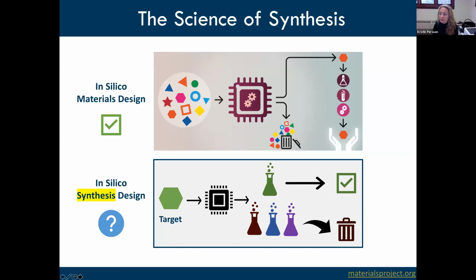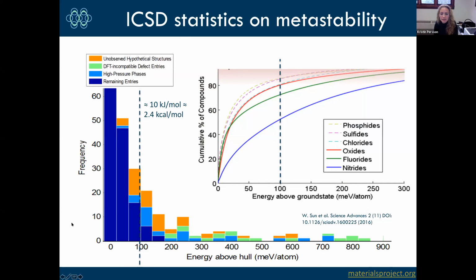So my group is doing a fair amount of this, and I'll give one example of the insights that we have garnered from looking at how we can bound synthesis space. If you look at some statistics out of the ICSD, the ICSD contains the materials that have been made. The Materials Project contains a lot of the ICSD structures and chemistries, but also our own hypothetical materials, things that we don't know if they can be made. And if you take just the statistics on the things that have been made, you can see that synthesizable materials really do correlate with energy above hull. That is something we can compute. We can calculate the energy of all the different competing polymorphs and see where you are in the metastability of things, how high you are above the basin of the lowest energy structures and the decomposition energy towards those.